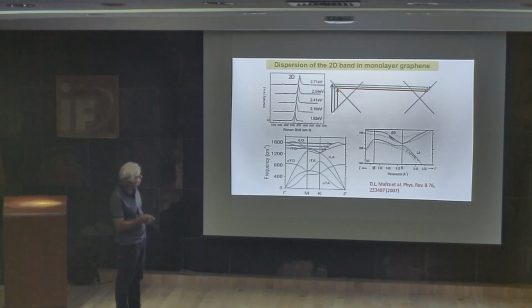If I have a blue photon, the resonance occurs at that point, and then the phonon has a still larger wave vector. And okay, this is what we call the phonon dispersion of graphene. In the case of graphene, we have 2 atoms per unit cell, so we have 6 phonon branches. 3 of them are the acoustic branches, and 3 are the optic branches.